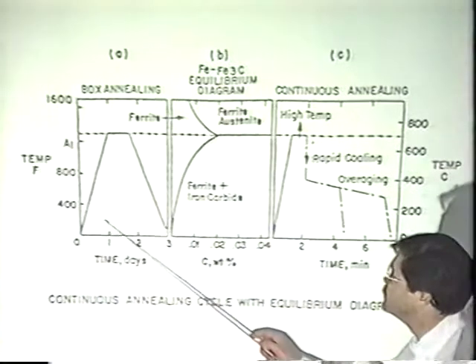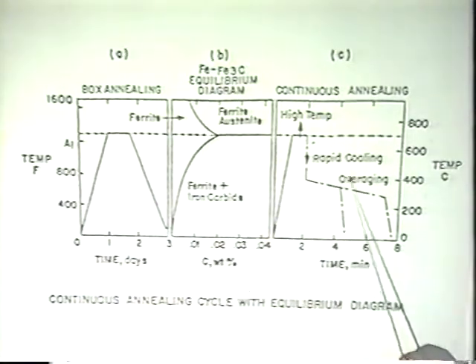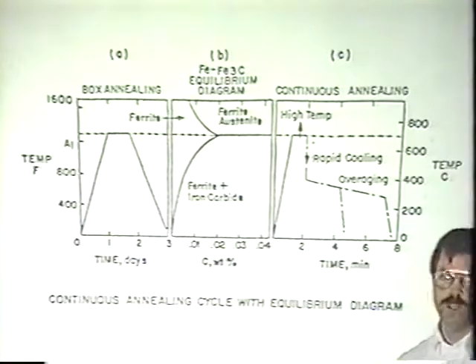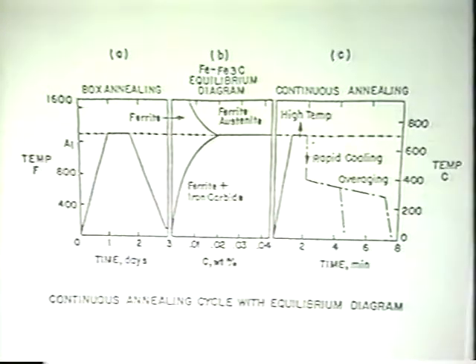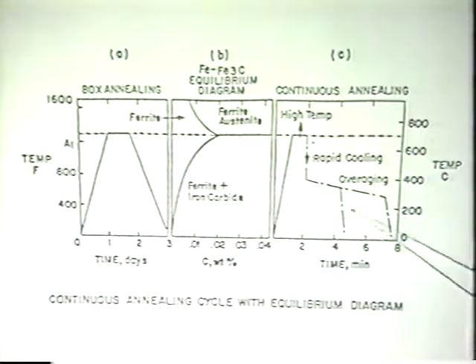Now, before we answer Tim's question here, we're going to go to this chart here. Let's compare now in time continuous anneal and batch anneal. Both anneal processes, whether it be continuous or batch anneal, take the steel up to a specified metallurgical temperature called A1. It's the critical temperature. You've got to get it above there. With batch anneal, we said earlier, for a CQ product, it takes about 3 days. Okay? And in the continuous anneal, it'll take about 8 minutes.